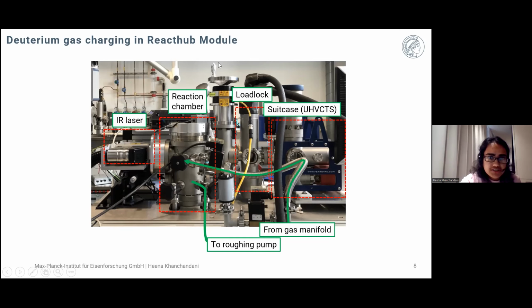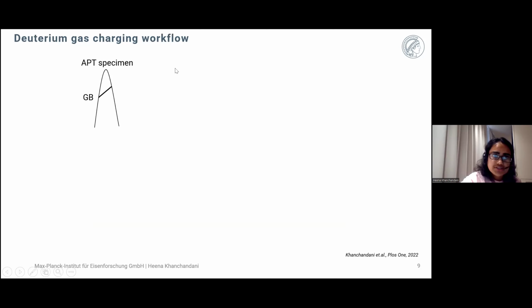So in this reaction chamber, the specimens can be treated in the presence of introduced gases at high temperature, for which it is equipped with an infrared laser, which is used to heat the APT specimens. And the suitcase can also be connected to this Reacthub Module to allow the ultra high vacuum transfer of these specimens. So here is the deuterium gas charging workflow which was followed.